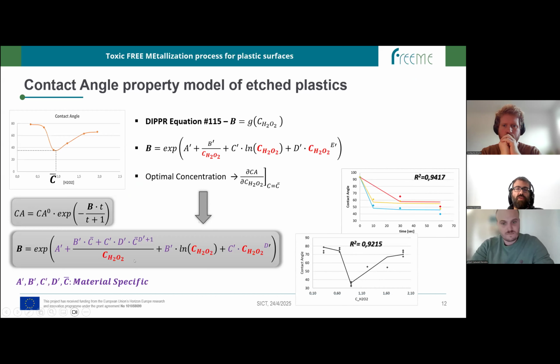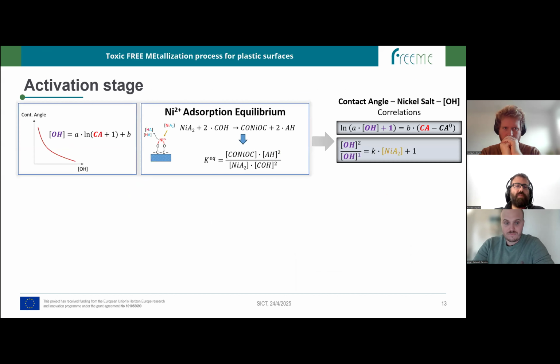And by this means, we have also fitted all these models to different kinds of experimental data coming from Creative Nano, which is also the experimental team developing the technology, and we have reached quite satisfactory R-square metrics. Quite briefly, there is also another model made for the activation stage, where we have made the correlation between the contact angle and the hydroxyl group's concentration on the surface, as well as the effect of the hydroxyl group's concentration on the surface versus the different nickel activation concentrations.